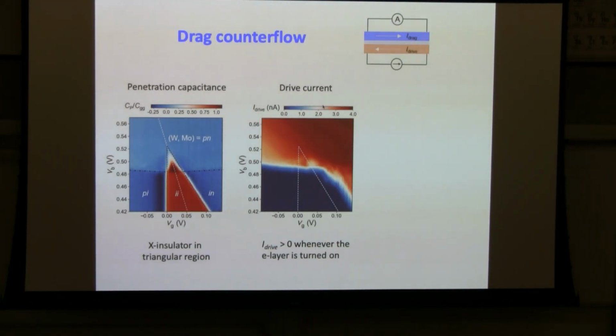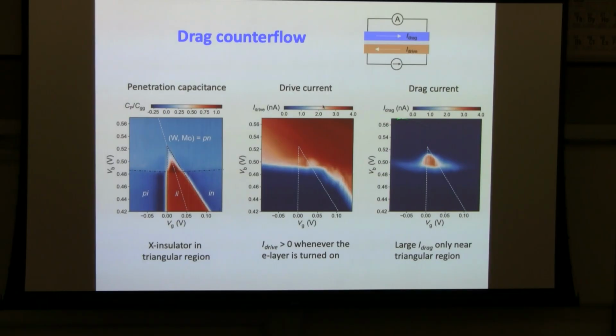Okay, so here is the data. Again, this is the compressibility map, VB and VG, of the charge compressibility. This triangle region is the excitonic insulator. And this is the drive current of the electron layer. Blue means no current, red means you already start some current in the channel. You can see that whenever there is an N in the phase diagram, you would turn on the electron layer, because that's where you dope electrons into the layer. So you get the current here, you also get current in the PN region. On the other hand, for the drag current, you only get substantial drag current inside this triangle here. Well, there's a little bit happening outside, and I'll come back to that later. But you get the large drag current only inside this triangle where you support the excitonic insulator.